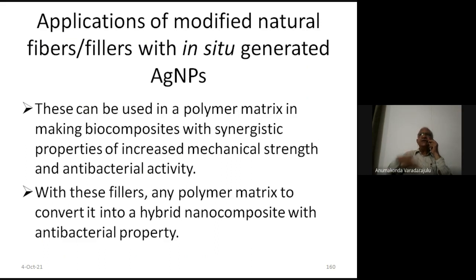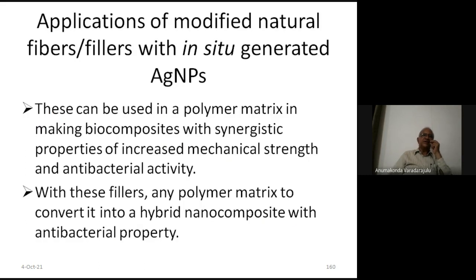So you can convert your polymer composite into a polymer hybrid nanocomposite with antibacterial property by replacing the usual filler with the modified filler with in situ generated metal nanoparticles, and the resulting composite is known as a hybrid nanocomposite with antibacterial property. So this is how we make these nanocomposites and biodegradable composite materials in our laboratory.